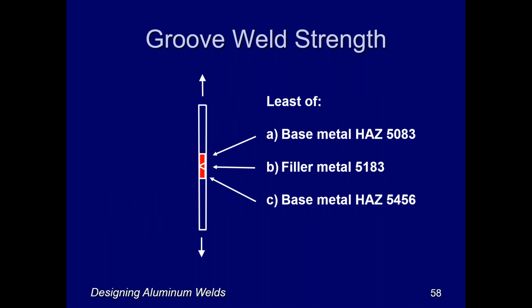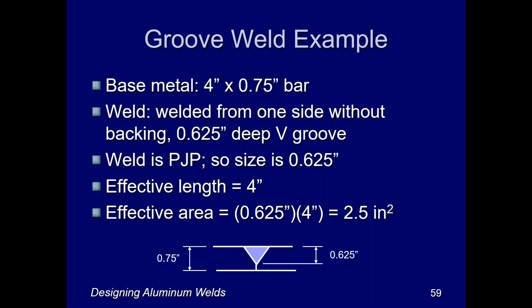And so the strength of a groove weld is really just another demonstration of the principle that a chain is only as strong as its weakest link. So we have base metal in the heat affected zone on one side of the joint, the filler metal in the middle, and the base metal in the heat affected zone on the other side of the joint. And let's say, for example, I'm welding together 5083 and 5456 with a 5183 filler. Well, in that particular case, I need to look at the strength of each of those three parts.